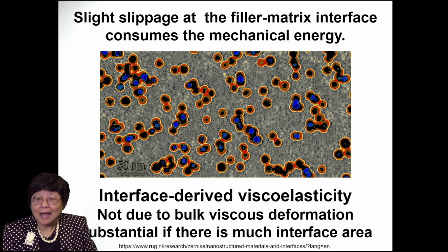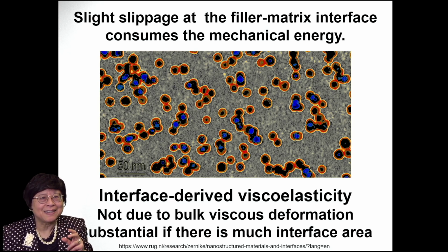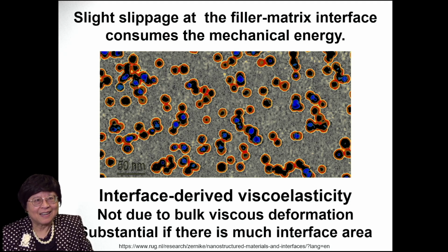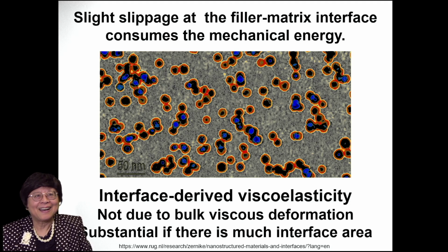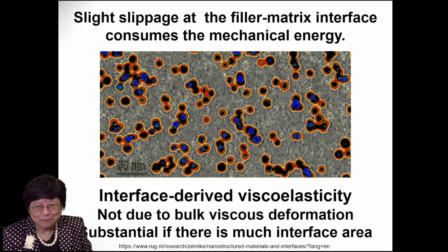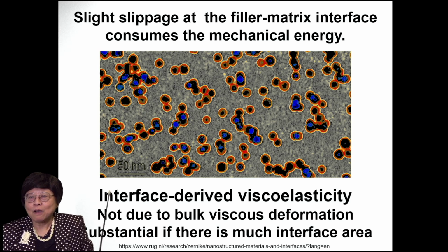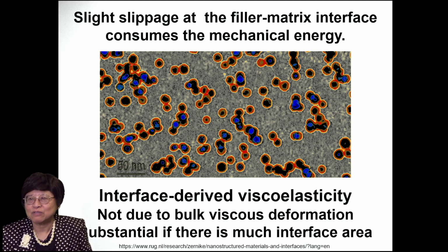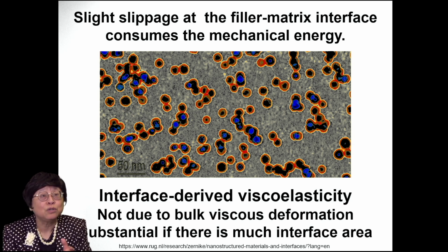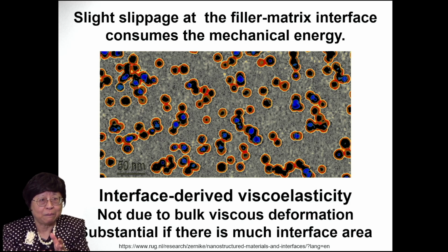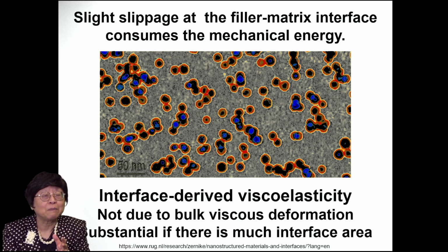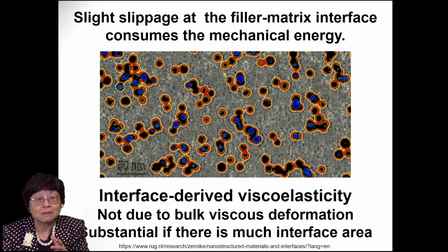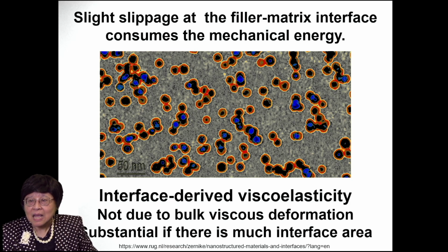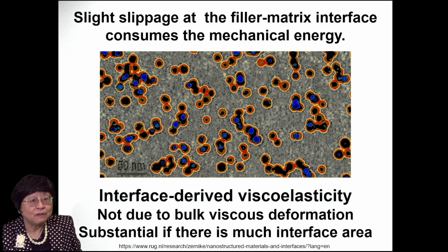And I had to devise a different mechanism of viscoelasticity. The usual mechanism exhibited by rubber is not good enough. And the mechanism I devised involves slight slippage at the filler matrix interface. I don't mean loosening the interface. It's just very slight reversible slippage during the vibration. And there's friction involved. And so this slight slippage consumes some mechanical energy, thereby providing mechanical vibration damping. And this I call interface-derived viscoelasticity.